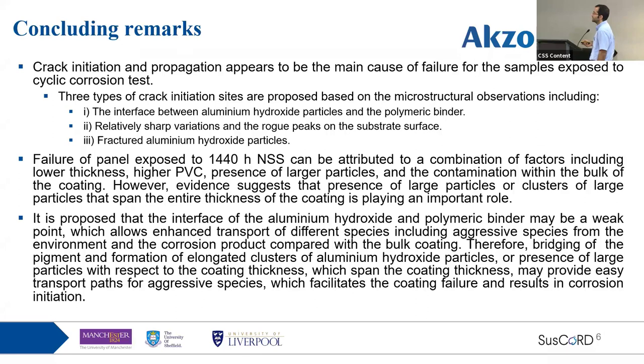And finally, it is proposed that the interface of aluminium hydroxide particles and the polymeric binder may be a weak point, which allows enhanced transport of different species, including aggressive species from the environment and corrosion products, compared with the bulk of the coating. Therefore, bridging of the pigments and formation of elongated clusters of aluminium hydroxide particles, or presence of large particles that span the coating thickness, may provide easy transport paths for aggressive species, which facilitate the coating failure and result in corrosion initiation.